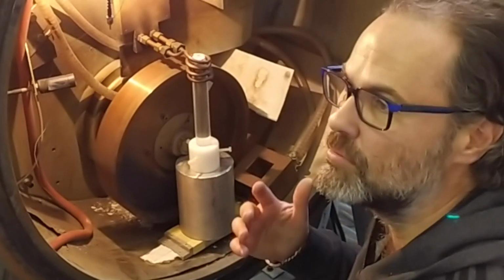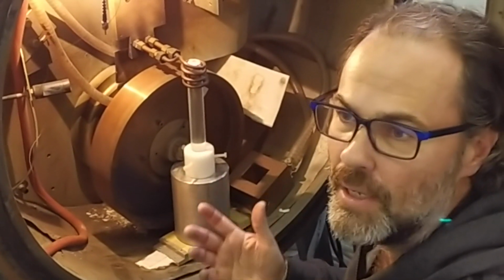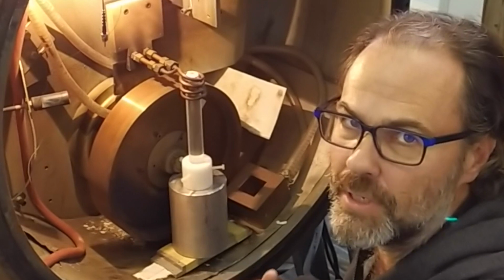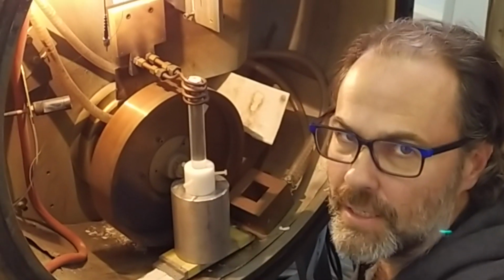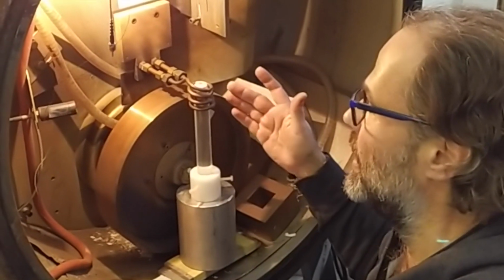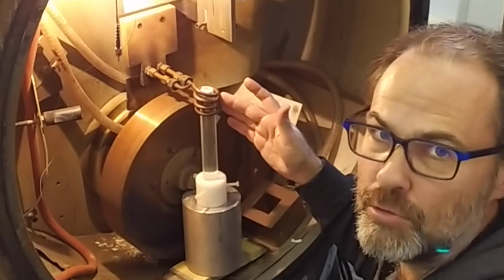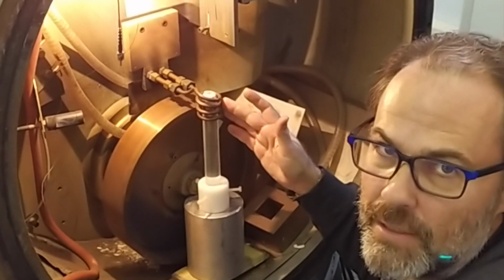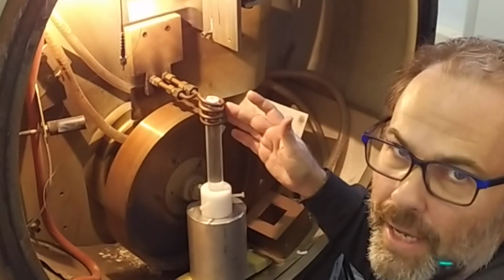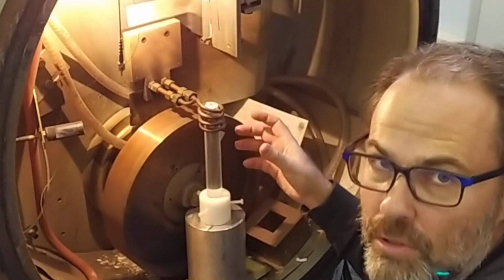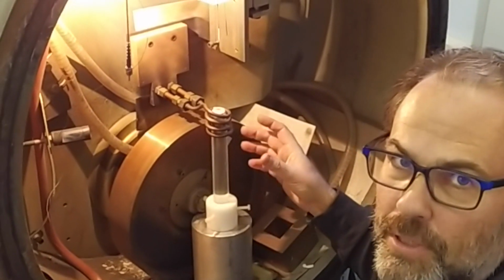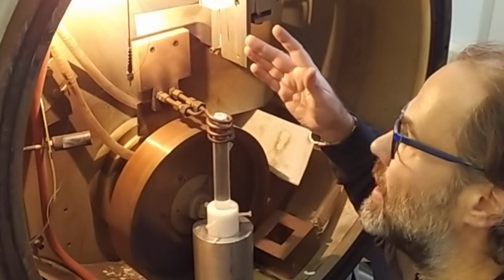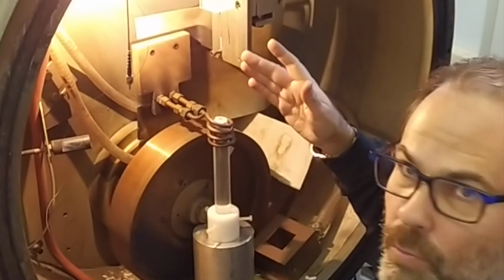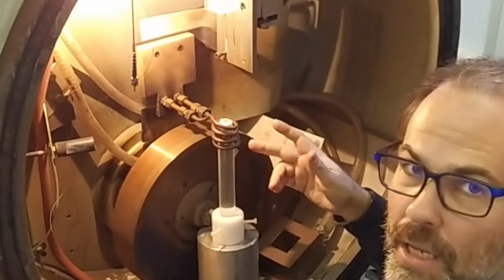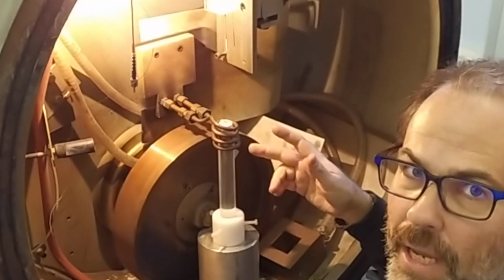You don't need too many components to set up an experiment for measuring the temperature of the medium in which the particles are dispersed. You need a copper coil that is used to generate the electromagnetic field and, of course, a power supply to drive it. Then you need a holder where you put the particles dispersed in the medium. And then you need a temperature sensor which you can immerse in the medium where the particles are located in order to measure its temperature.